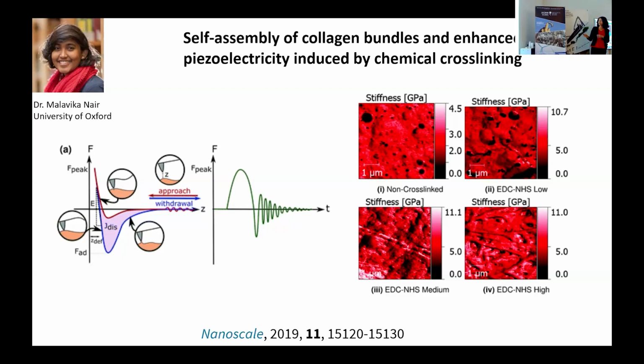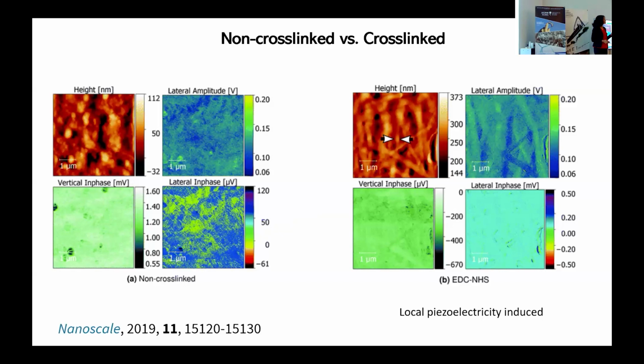But in my group, we tried an experiment where we looked at non-cross-linked collagen versus cross-linked collagen using different cross-linkers. The first thing that she saw is that the stiffnesses can be quite different depending on the cross-linking that you use. But more interestingly, I think at least, there's a difference in the piezoelectric response. Here is the topography, and the rest are piezoelectric PFM images, for non-cross-linked versus cross-linked collagen. If you look at the lateral amplitude, because this is another molecule that has shear piezoelectricity, so you see it in plane in this case, you can start to see the emergence of bundles in these cross-linked samples, which also have a piezoelectric response attached to it.